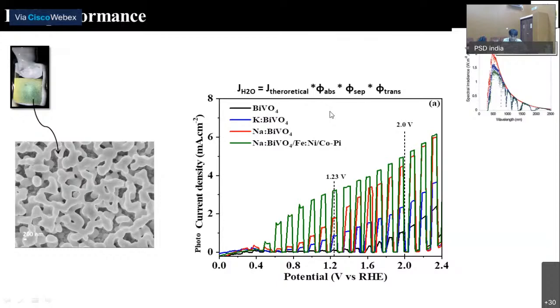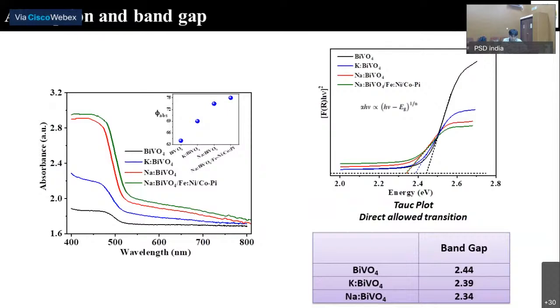So we have systematically analyzed all these 3 efficiencies. First is the absorption efficiency. We have used a UV visible spectrometer to analyze the absorption of this doped and undoped bismuth vanadate system, and you can see the calculated absorption efficiency. With the doping, it increases, and especially with the sodium doping, it increases the most. There might be 2 reasons for that. One, whether the absorption spectral region is increasing with the doping. With the absorption spectrum, we see that the absorption spectral region is not increasing.